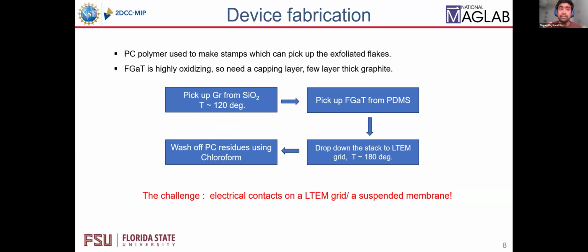After exfoliation of the sample, the next step is to pick up the sample from the substrate. For that, we make a PC polymer stamp, which can pick up the exfoliated flakes from the silicon wafer. First, I pick up graphene from silicon oxide. In the glove box, we had the transferring setup where we increase the temperature up to 120 degrees Celsius and slowly pick up the graphene using a stamp. Then, using the same stamp with graphene, we pick up the FGT from PDMS. So this was the pickup process I was following.